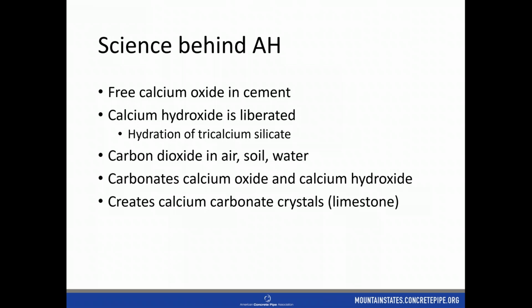They're creating that calcium carbonate, and it creates this limestone, and it starts filling in the holes, and it seals these cracks. And what it actually does, it's very fascinating. It seals these cracks, and it protects the steel from corrosion.